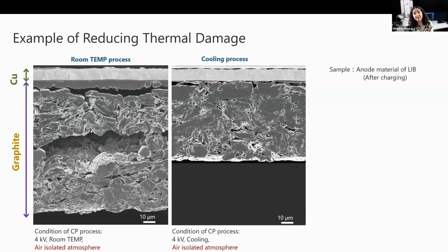The next example highlights the benefits of using cryogenic temperatures when cross-section polishing to mitigate thermal damage. This sample, which is an anode material post-charging, develops a thermally unstable film on the graphite of the negative electrode, necessitating cooling during preparation. So the room temperature preparation on the left shows significant deformation and void formation, likely due to the heat generated during the milling process. In contrast, the cryogenically cooled sample on the right displays a uniform graphite structure with a smooth, undistorted cross-section.